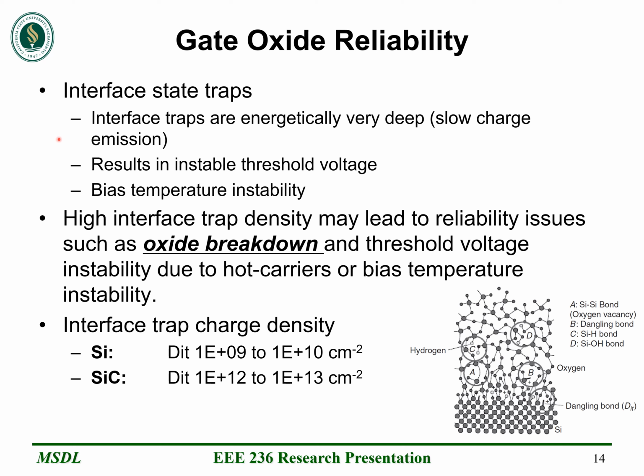These interface traps are energetically very deep, which means that for whatever charge is trapped, it takes a very long time for that charge to detrap. This can lead to unstable threshold voltages and bias temperature instability. And what's much worse is that at very high interface trap densities, this can actually lead to premature oxide breakdown.